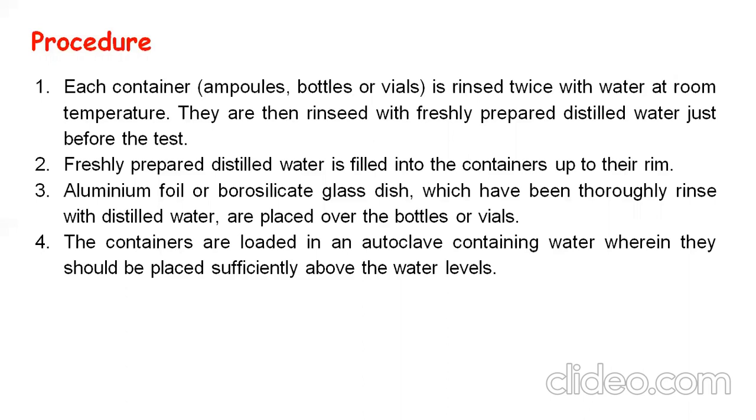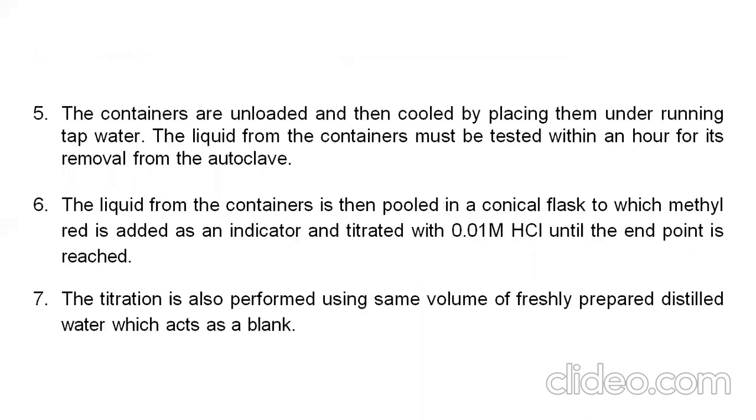Aluminum foil or a borosilicate glass dish which has been thoroughly rinsed with distilled water is placed over the bottles or vials. The containers are loaded in an autoclave containing water, wherein they should be placed sufficiently above the water level. The containers are unloaded and then cooled by placing them under running tap water. The liquid from the containers must be tested within an hour of its removal from the autoclave.